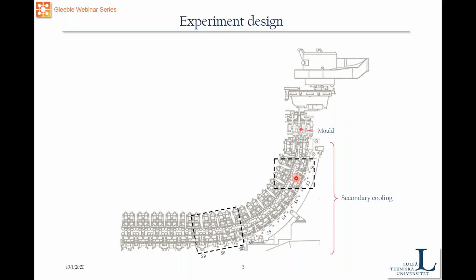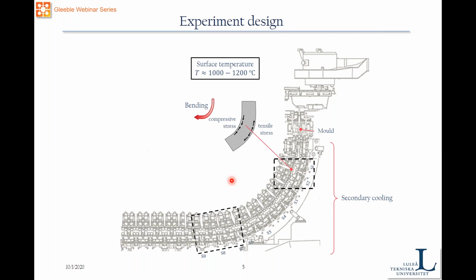What we did here is identify 2 main zones that might be risky for crack formation during continuous casting, which are the bender and the straightener. As its name says, it is bending. It requires deformation of the material. The temperatures here are oscillating around 1,200 degrees. So here, the material is subjected to a combination of compressive and tensile stresses.